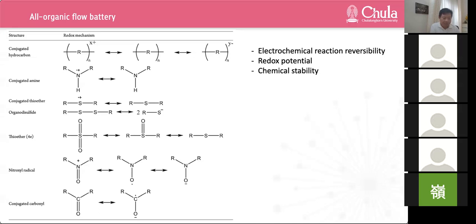Two size exclusion-based strategies have been attempted to overcome this limitation. The first strategy involves reducing the membrane pore size to increase selectivity. And the second strategy is to put redox moieties onto polymeric backbones. And this method has also been tried with water-soluble polymers in an aqueous flow battery. However, the conductivity of membrane and the solubility of redox polymers still remain a concern.